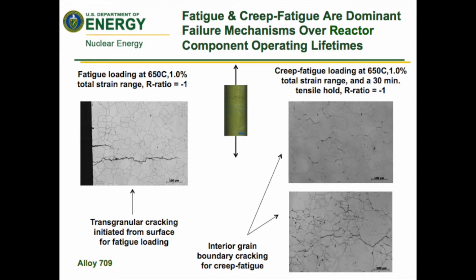Actually, any of these classes of high temperature materials, fatigue and creep fatigue, are very dominant fracture mechanisms, failure mechanisms that are going to be operative over the reactor component lifetime. And these are illustrated at the microstructural level by some of the micrographs that are shown here. On the left-hand side, you can see the kind of transgranular cracking that would usually begin at the surface that would be associated with pure fatigue loading, as compared to the intergranular cracking that would initiate deeper in the specimen from creep fatigue loading, and that you see with 650 C with a 30-minute hold time. So these are the types of